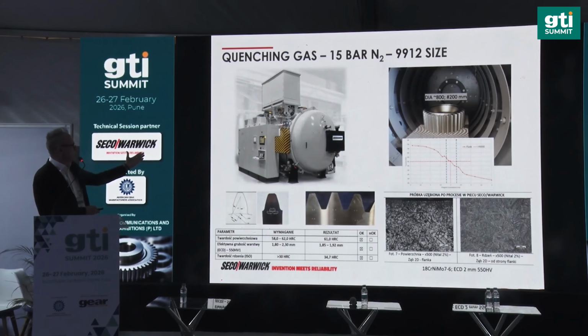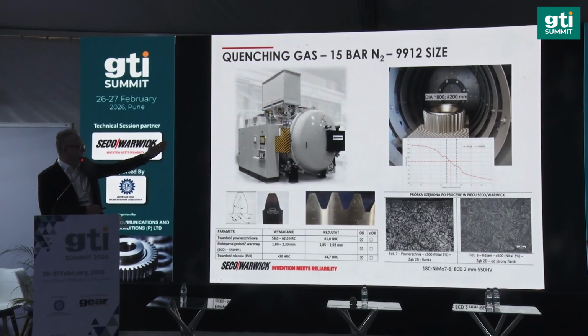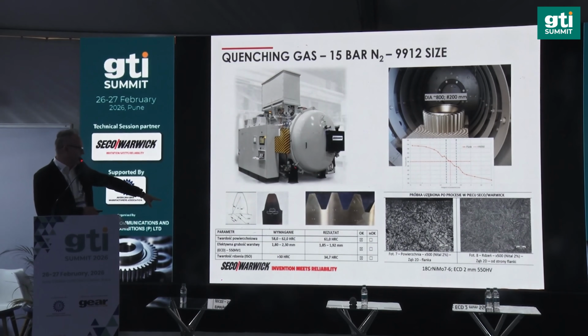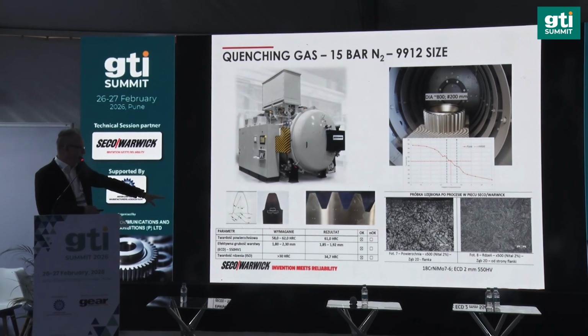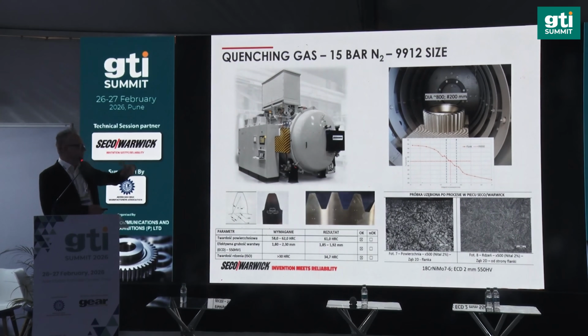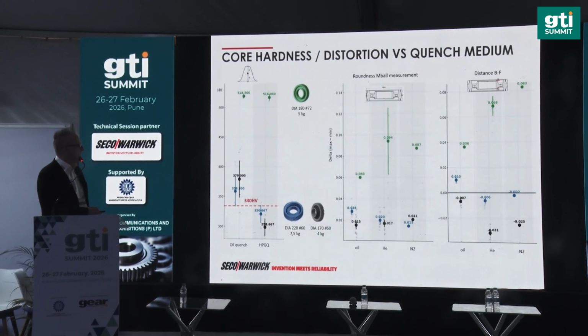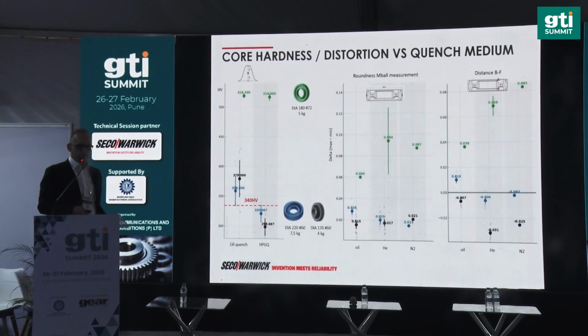In this particular case, we are considering a single chamber furnace of size 900 by 900 by 1200, case hardening a gear of diameter 800 millimeters and thickness 200 millimeters, with a requirement for core hardness of more than 30 HRC. And after processing of that part, we received core hardness at the level of 35 Rockwell hardness, which means that even for such massive parts, we can transition into high pressure gas quenching technology. If we cannot, we still can transition into oil quench technology.